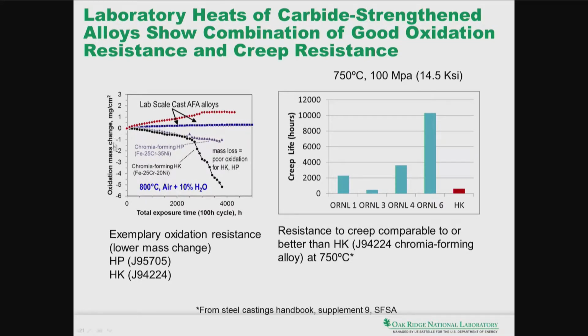And you can see that on the y-axis what you're looking at is the oxidation mass change normalized with the surface area, that is how many milligrams per centimeter squared, as a function of 100-hour exposure cycles. And this is the total life. This is like 5,000 hours. And you can tell that the AFA alloys retain a very low mass change, whereas the HK and the HP alloys, for example, start shedding a lot of the oxide, and there's significant mass loss. On the creep side, again, these are experiments done at 750 C at 100 megapascals, and you can see that the HK alloy lifetime would be somewhere here, a couple of 100 hours perhaps, and we have lifetimes going up to 10,000 hours under similar conditions. So the alloys not only have good oxidation resistance, but also have good creep resistance, as outlined here.